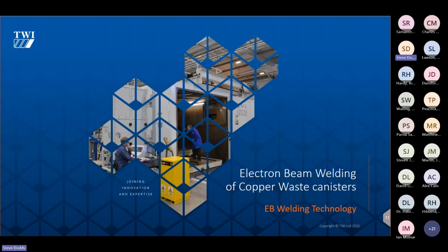Another technique that we could use here, either for the copper or for the steel elements of the canister, is electron beam welding. So electron beam welding, as some of you may know, is an autogenous welding technique with a very precise and high quality beam. And the surface finish in general is excellent. In fact, it's often used to redress joints. And it can go to very thick penetration. However, standard EB welding can often leave quite a sharp root tip at the very bottom of the weld, which isn't great for the sort of modeling that we were looking for and the microstructural abruptness, the changes in microstructural texture that we were getting.